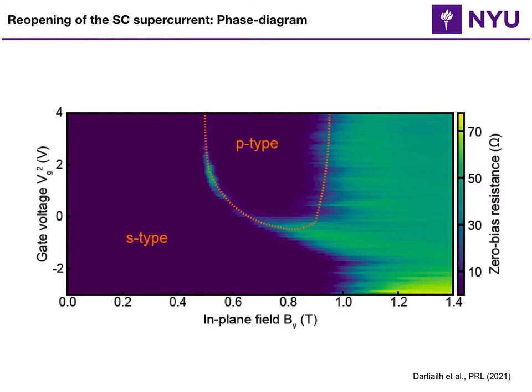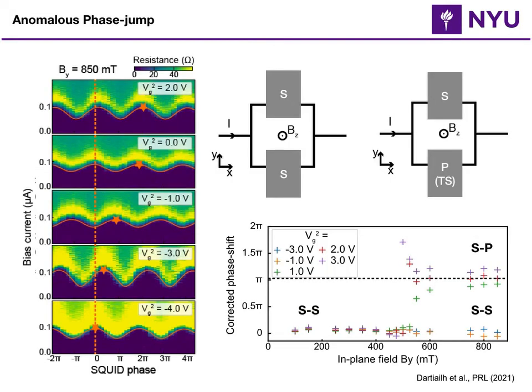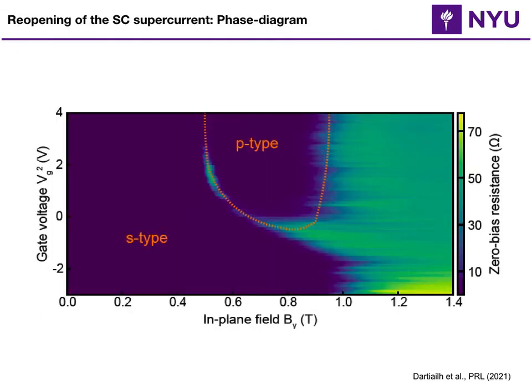So this is great, but it still is not enough. It would be great if we get more information and a more conclusive signature here, right? So we put these devices on a SQUID loop and we try to measure the phase as we transition from S to P-type state. For example, here I'm showing you a graph at 850 millitesla. This is a field that is strong enough that by just sweeping the gate voltage, I can actually go from S-type to P-type.